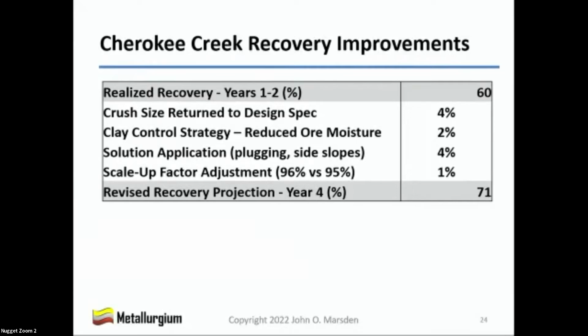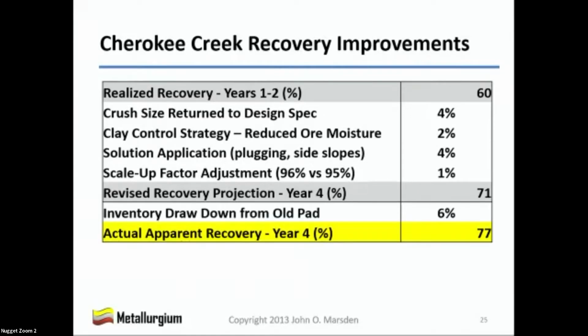Then she thought about it a bit more. Next slide, please. And she realized that if she accelerated the placement of liner, she could actually get inventory drawdown from the old pad. And if she did that, she was going to get that 6% of inventory off the old pad. She would start to build up inventory going forward. But she figured that really the overall apparent recovery at the end of year 4 was really going to be about 77%.